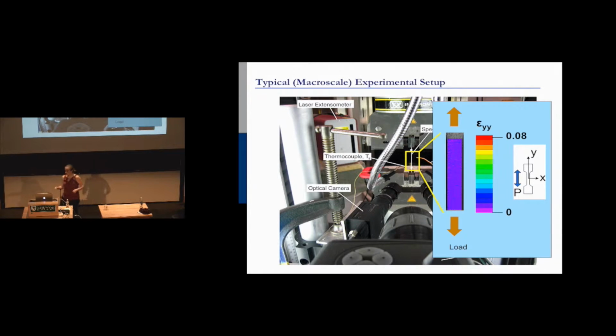And so you start out in this austenite, and you're tracking all these dots with relation to each other. There goes the martensite. I mean, it's a really sharp band. And it comes up, so that's 6% strain, and the purple's 1% strain. Hugely localized strains. And then when you release, it comes back with nearly perfect recovery.